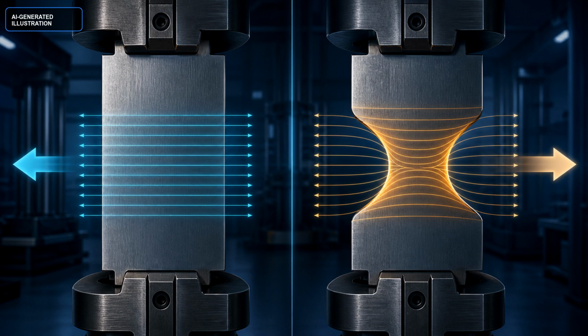Imagine the same nominal force entering two coupons, one smooth, one with a small shoulder notch. The average force divided by the average area can be identical, but at the notch root, the load path bends sharply and stress lines crowd together. That local stress concentration can be several times the nominal value, depending on the radius and geometry. So below yield is incomplete unless we say where the stress was measured. A macroscopic gauge can look elastic while a tiny region at the notch slips irreversibly.